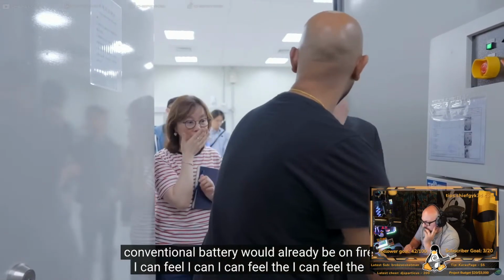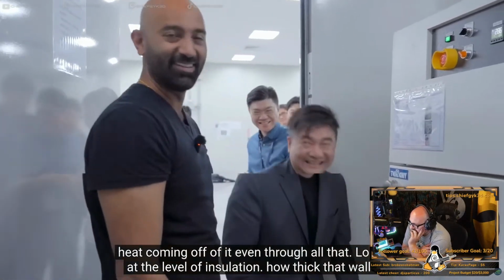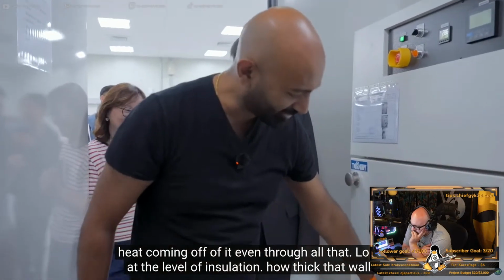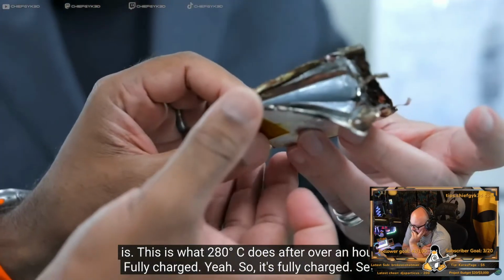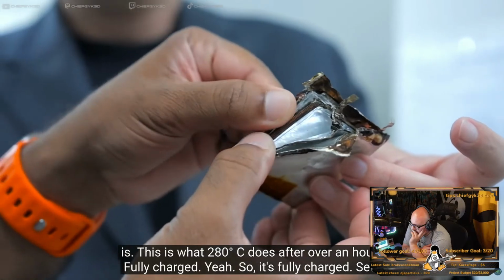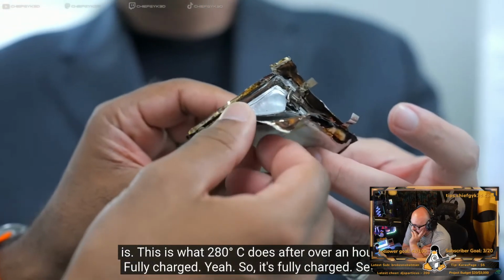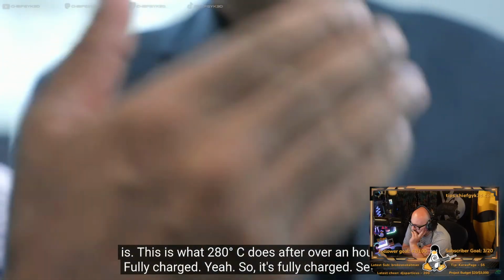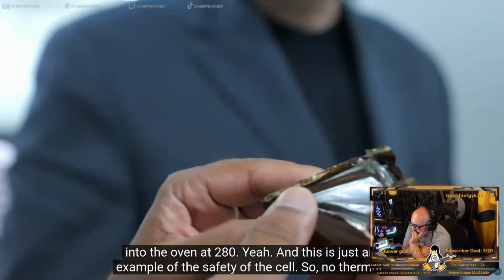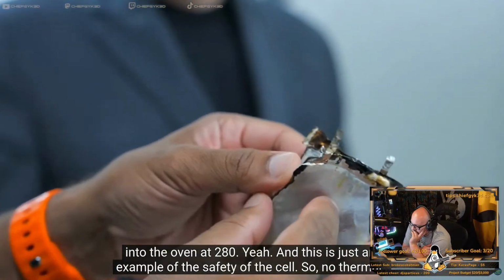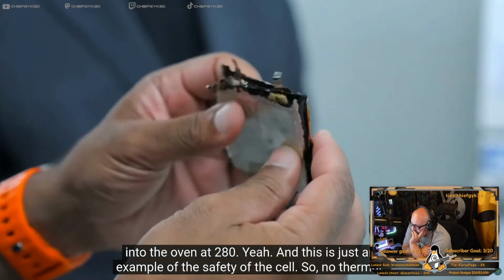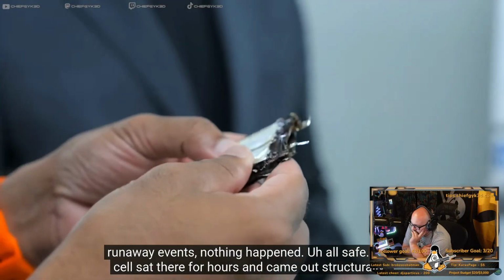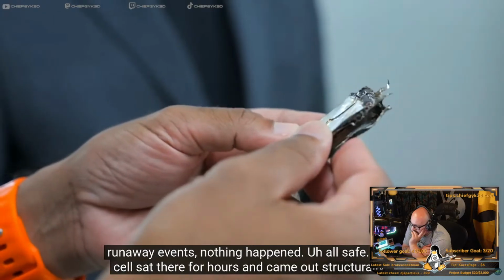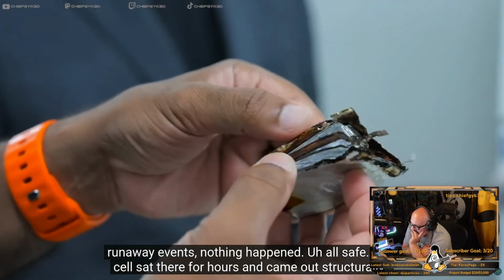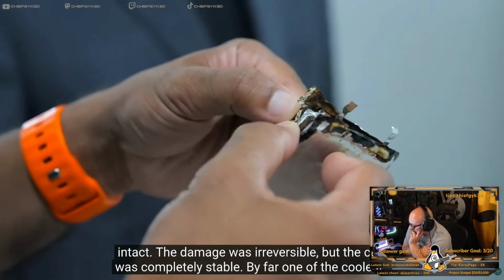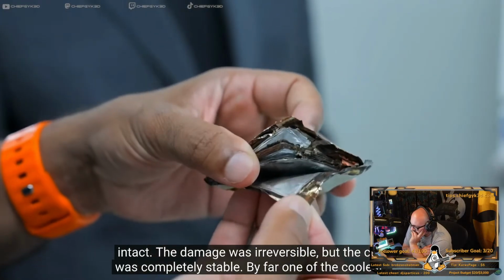I can feel the heat. Damn. Even through all that, look at the level of insulation, how thick that wall is. This is what 280 degrees Celsius does after over an hour. So it's fully charged, set into the oven at 280. And this is just an example of the safety of the cell. So no thermal runaway events, nothing happened. Wow. All safe. I mean, it looks destroyed, but it came out structurally intact. The damage was irreversible, but the cell was completely stable.